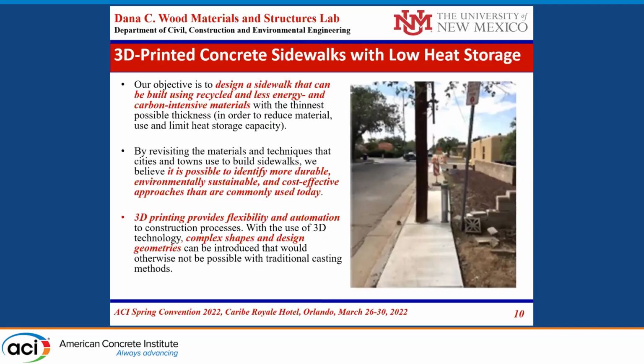So using this concept, we were looking at, can we use 3D printing for sidewalks? The idea here is the issue of heat storage: concrete with materials that have high heat storage absorbs a lot of heat during the day, and this concrete will be releasing this heat out in the evenings. So if we can use materials with low heat storage in the concrete, we actually can create a lower heat material and design sidewalks that can be built.